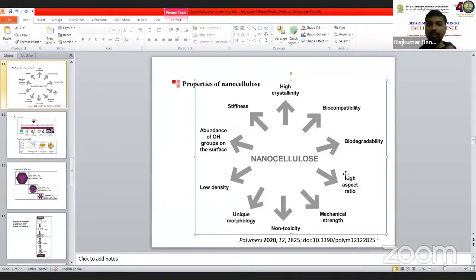The good thing is they have good mechanical strength. The cellulose chain is very strong, with strength almost higher than stainless steel. They have good mechanical properties, stiffness and low density. This is also an important property. Cellulose has very, very low density, like 1.5 grams per cubic centimeter almost. Sorry, the expression may be wrong. So cellulose has the lowest density, a very lightweight material.